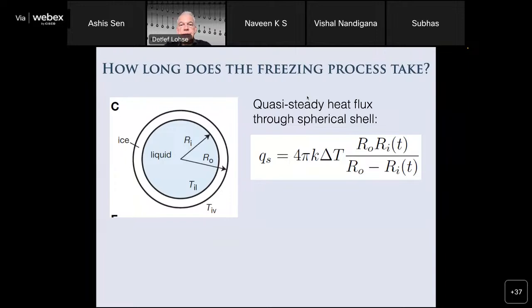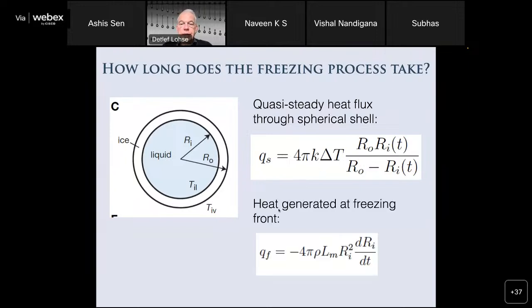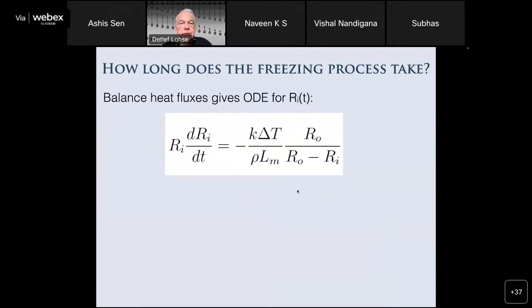And what you have to balance is the quasi-steady heat flux through the spherical shell, which you can easily calculate here with the heat conductivity. And this is compensated by the heat generated at the freezing front. And this is, of course, determined by the latent heat Lm. You just balance these two, and then you get a simple ordinary differential equation for the radius of this freezing front, starting at the radius of the drop and then going inwards.